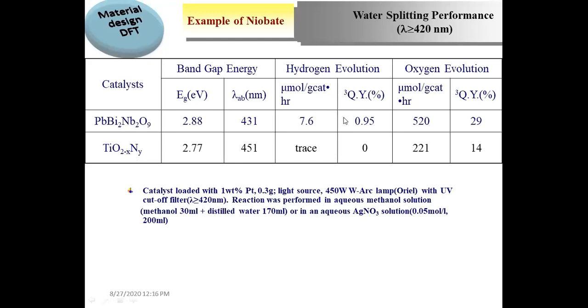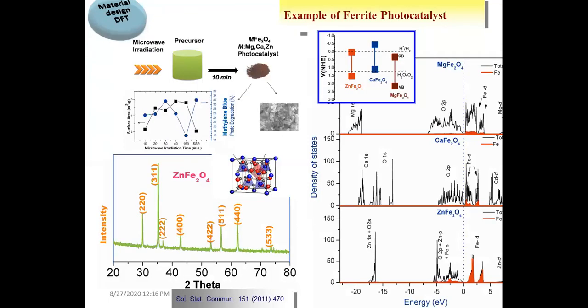So you see the efficiency of hydrogen evolution and oxygen evolution of lead bismuth niobate is very high under visible light as compared to titanium oxynitride. So this tells us that just doping is not a good way to do that, and lead bismuth niobate indeed was a good system. Then as time evolves, there are possibilities that one can get various new systems. We can design new systems to get highly efficient photocatalysts.